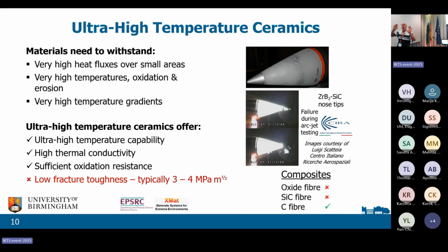Right, so what do we do when we're lacking toughness in ceramics? We reinforce them. We put fibers in. If you think about it, we've got oxide fibers. They're limited to 1200 degrees centigrade, absolute maximum. You've got silicon carbide fibers. If you really push them, you might get 1800 to 2000, but they don't like it. But then you've got carbon fibers, and carbon fibers are really good, but they need protection from oxidation.